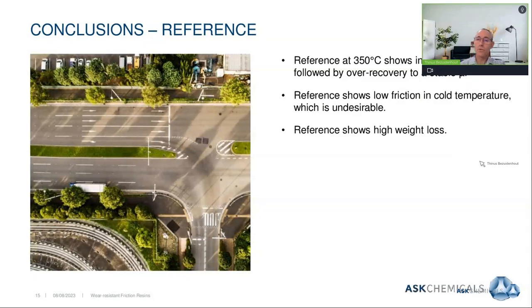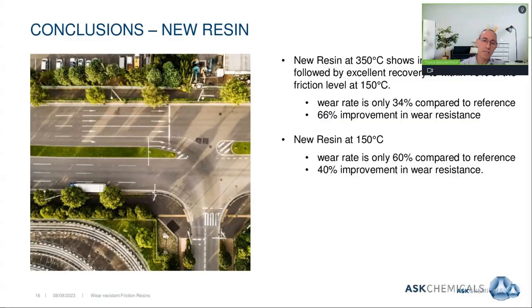And now I want to draw your attention to the conclusions with the very latest technology. What we saw in the cross testing was initial green fade followed by very good recovery within the 10% variation limits of the friction level at 150. We saw that the wear rate was only a third compared to the reference. In other words, about a 66% improvement in wear resistance.